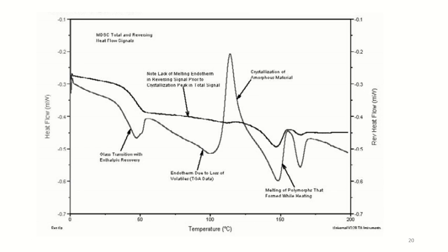Since melting happens after the cold crystallization exotherm in the total signal, the sample was primarily amorphous.